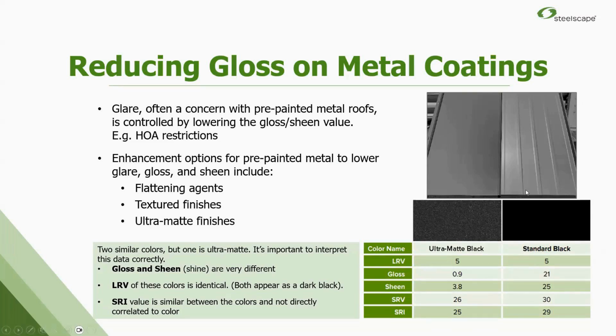And we showed here the LRV is the same. Gloss is vastly different. This one on the left only has a 0.9 gloss while we're up at 21 on the standard. Sheen, again, 3.8 versus 25, huge difference. But look, the solar reflective values are almost identical. So we can drop that gloss, drop that sheen, get that matte finish, and still have the high energy efficiency numbers that we need.